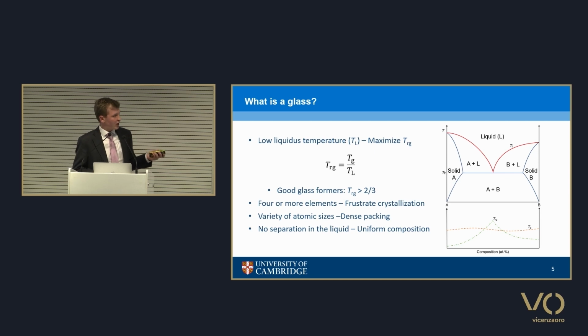Those atoms we choose quite carefully. So our elements are chosen for varying atomic sizes. This helps promote the dense packing. And we also want to make sure that chemically they all like each other the same amount so that we don't get any phase separation.